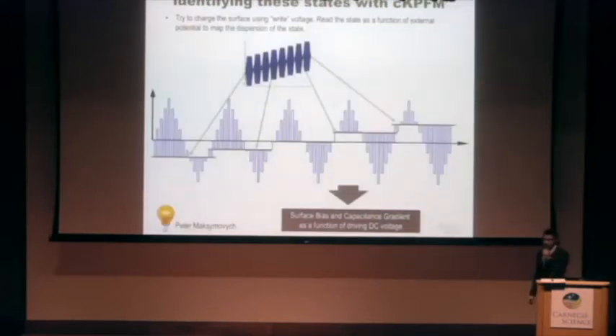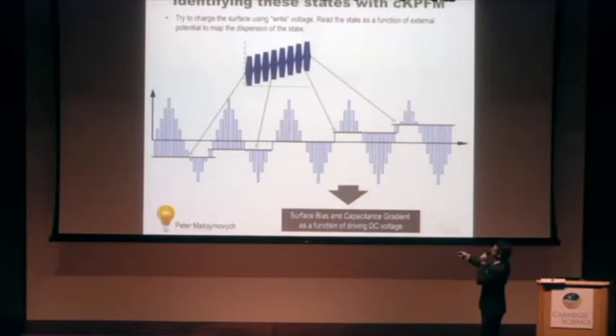How can we possibly identify some of these states? For that, we turn to a technique called contact Kelvin probe force microscopy. This is basically where you take hysteresis loops, but instead of reading the piezo response at 0 volts, we now read the piezo response at different voltages. So in this case, -2, -1, 0, 1, and 2. You can forget about this BE packet here. This is just the read packet. So basically, this is what's applied, and you're reading the signal at different voltages.